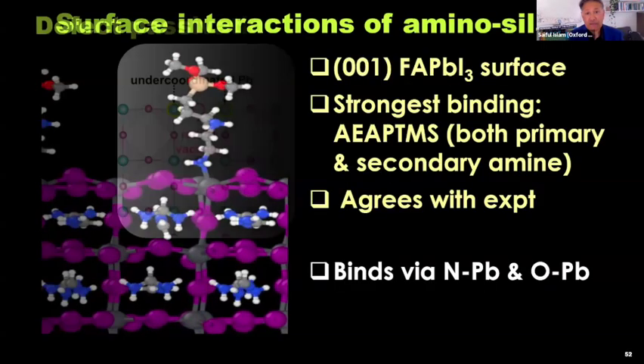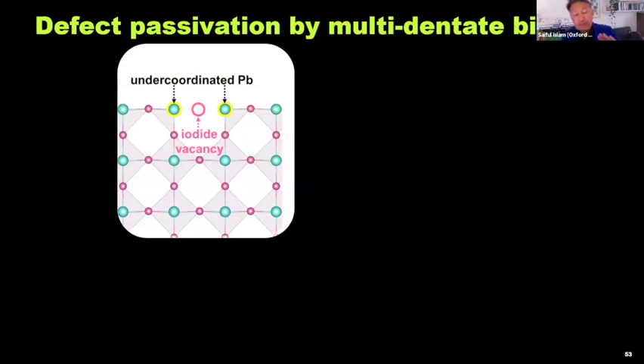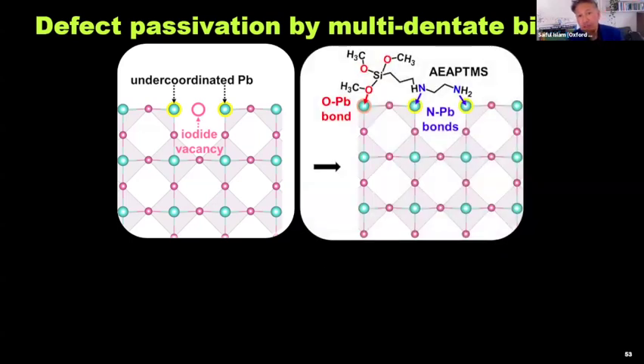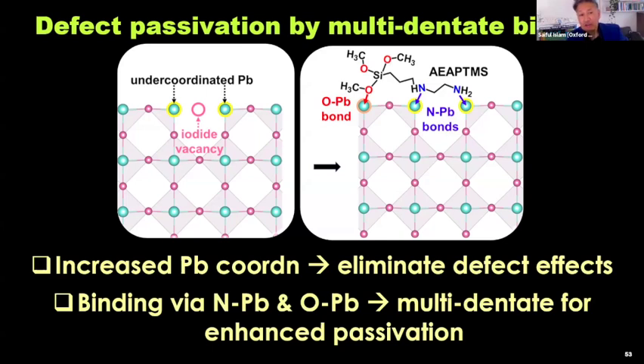So let me show that as a schematic. On the left is the pristine surface, showing the undercoordinated lead next to an iodide vacancy. And this is the final simulated surface, where the aminosilane now bridges that undercoordinated lead with lead-nitrogen bonds, but also bonds to another lead through the oxygen. So we're showing multidentate binding. We're increasing the lead coordination, eliminating the effect of the defect, with strong binding and multidentate passivation. So basically, this could be a passivation strategy using aminosilanes for durable, stable solar cells. And we're doing further work to understand and predict some other molecules as well.